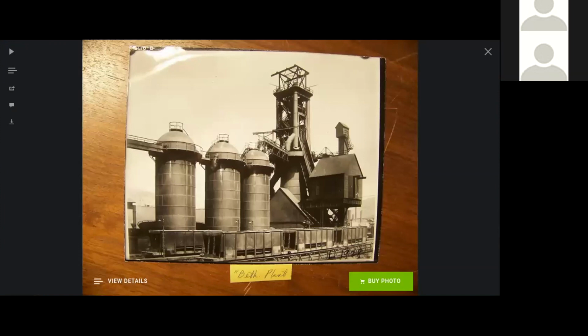Now, one thing to note is that you only need one stove at a time to actually provide hot air. But because you can only have one stove pumping hot air and the other one being warmed up, you'd actually rotate between the stoves. So you'd have usually a minimum of 3 stoves. One would be warming up with gas being burned inside of it. The other one would have the cold air going through and being heated by the pre-warmed bricks. And then the other one would be in reserve in case you had some sort of issue. And some furnaces had up to 5 stoves.